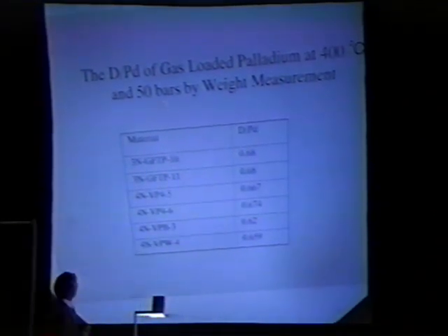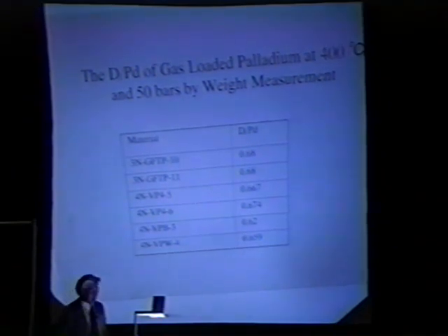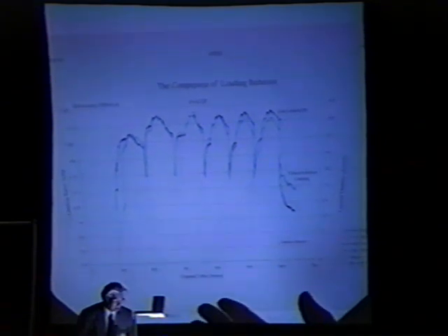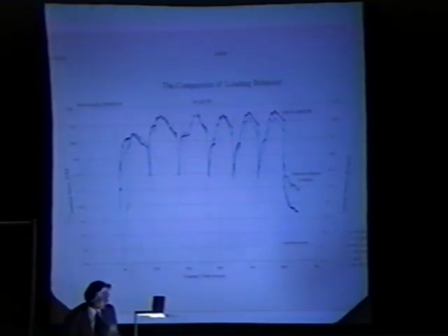About 0.62 to 0.68 loading ratio is attained by high temperature and high pressure gas loading. This is a typical loading behavior.